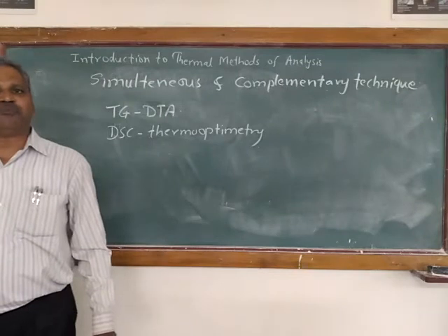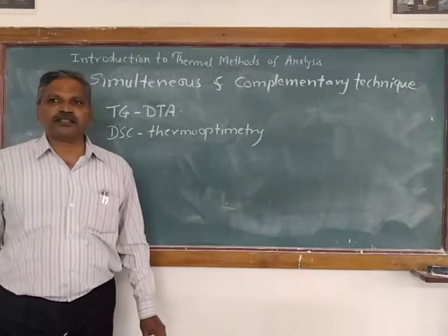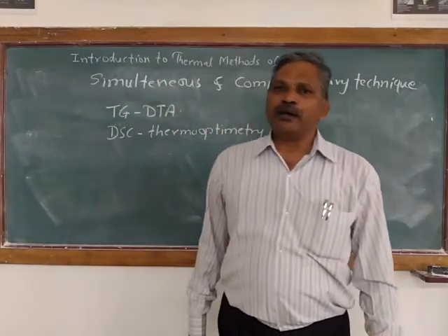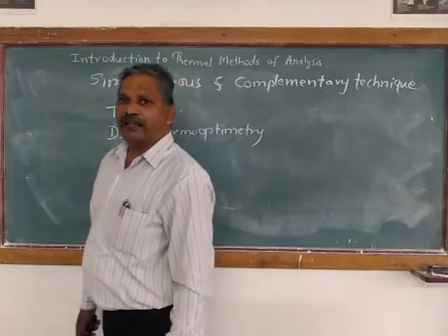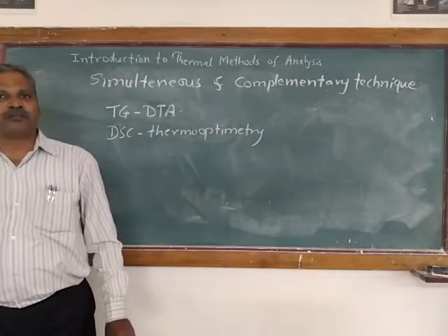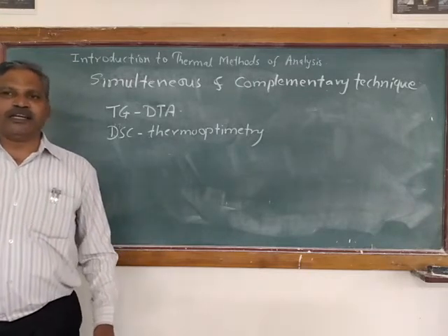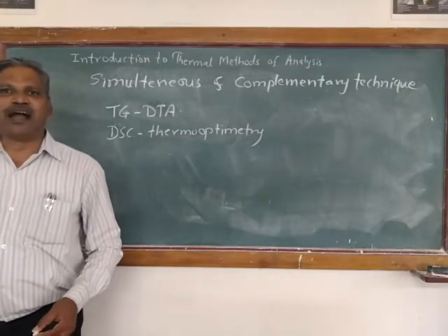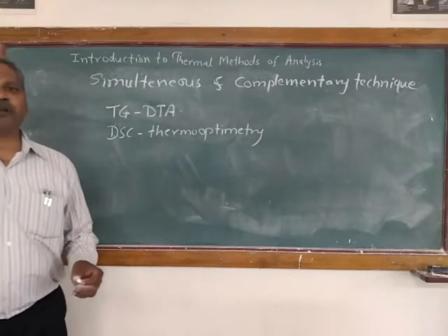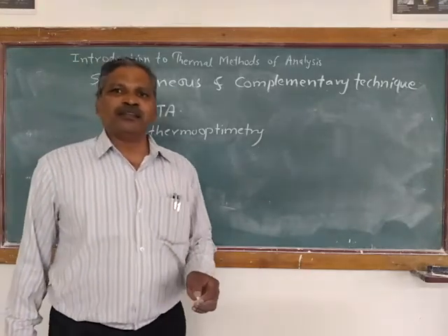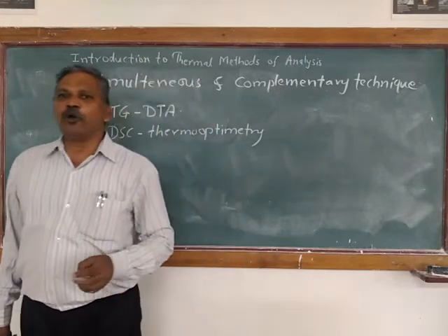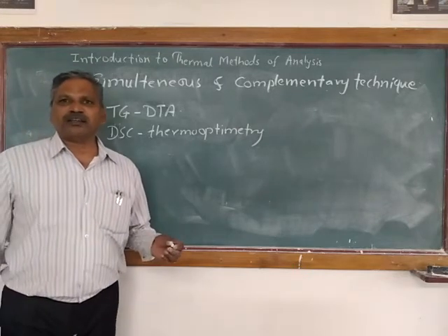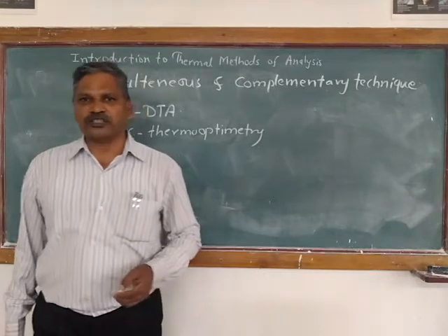Simultaneous techniques are to be preferred since different samples and different conditions may alter the thermal analysis curve. However, optimum conditions may be very different for the two methods. For example, if you are performing the DTA experiment, the highest sensitivity is attained at high heating rates. But if you are performing TG simultaneously, then the best resolution is attained at low heating rates. So, in the case of simultaneous techniques, the different techniques will have different experimental conditions.